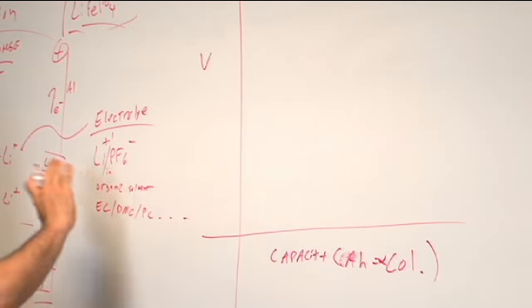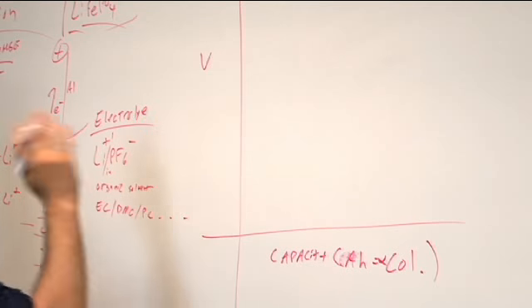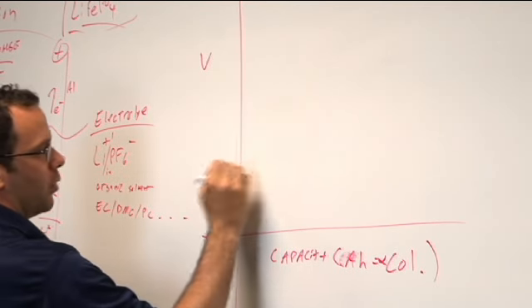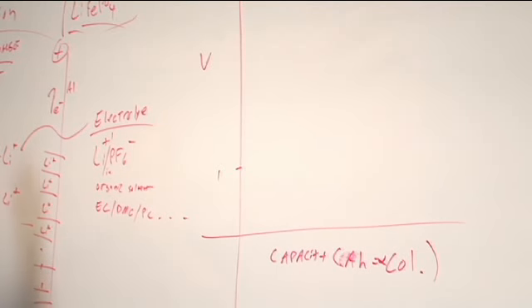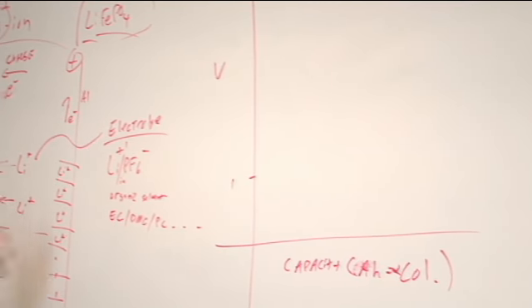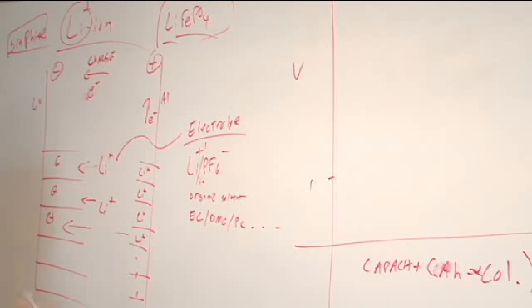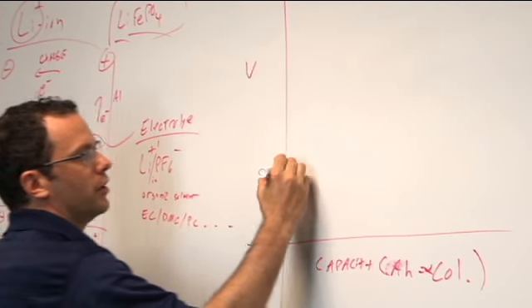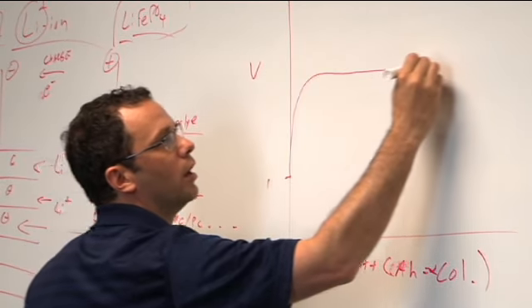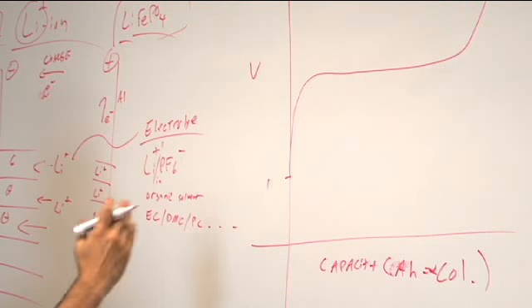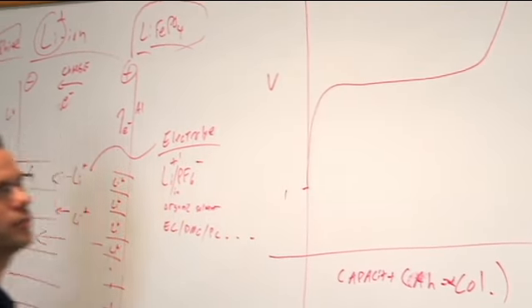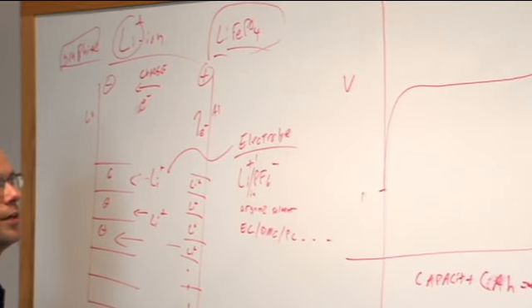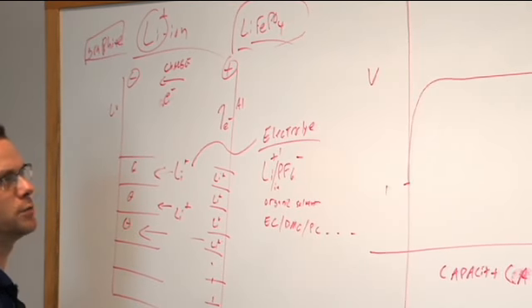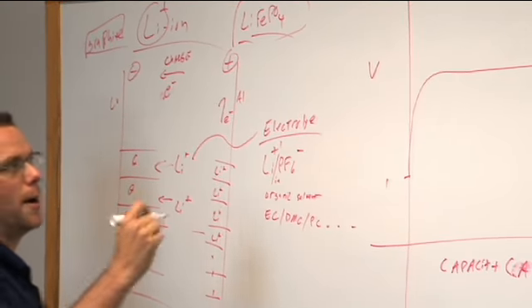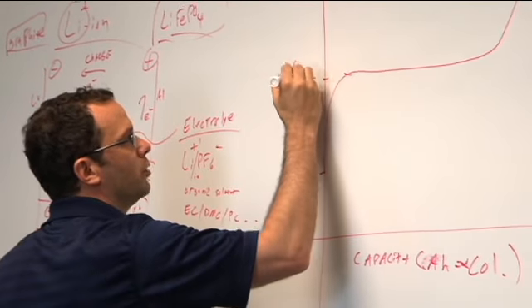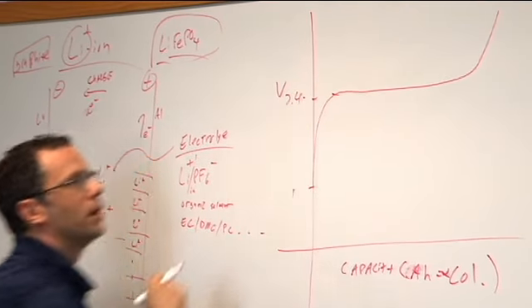All right, fine. And we start at our open circuit fully discharged state, which is something like 1 volt. And that's just the natural equilibrium surface potential of our lithium iron phosphate versus our graphite without anything. And it quickly does this. It jumps up and gives us a plateau, and then goes up like this, okay? This is a sort of idealized lithium iron phosphate charge curve, but you've seen data similar to this both from the manufacturer specs and also from probably your own testing. And this is about 3.4, 3.5 volts, okay? So there's this plateau.